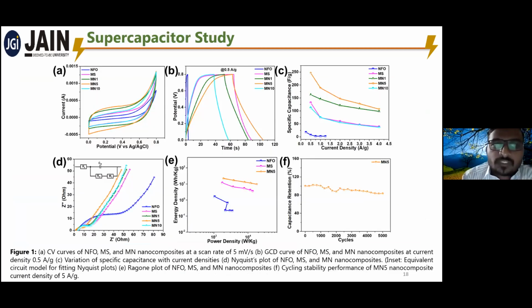Now the supercapacitor performance. From the CV curves we can see that the area of the CV curve of Mn5 is larger. That means there are more active sites available in that composite compared to the bare materials as well as the other two materials. From the GCD we can see that the discharging time is increased compared to the bare materials. That clearly evidences that the synthesis of the nanocomposites is much more beneficial compared to using the solo materials in various applications such as supercapacitors.